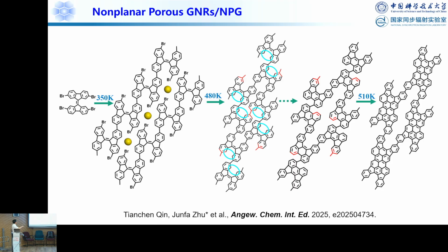One side tilts down, close to the surface, and the other side tilts up. So then this so-called asymmetric debromination reaction happens. You first form this one, and in between there's a gold atom here. When you first increase the temperature, the Ullmann coupling happens again, and then you form porous graphene with a very narrow gap in between. Finally, if you increase the temperature, you form these very big pores on the surface.